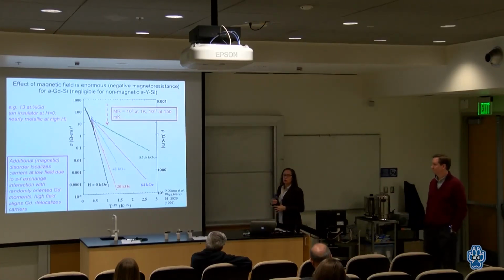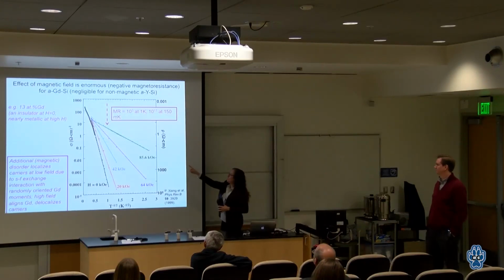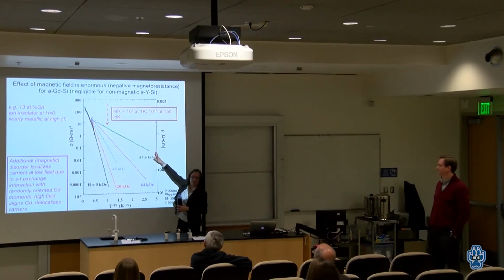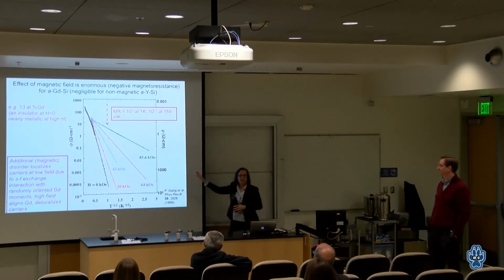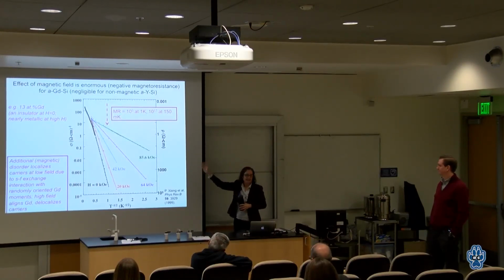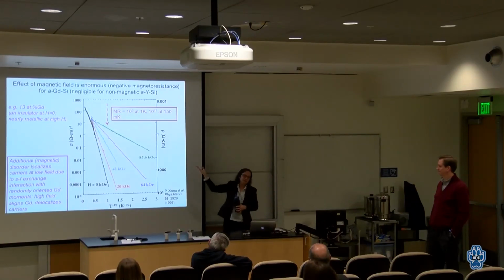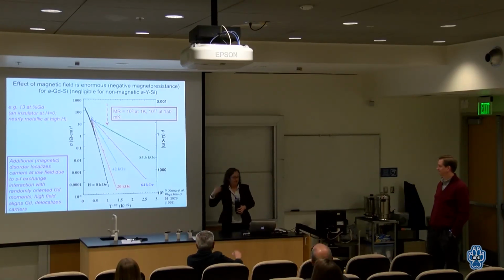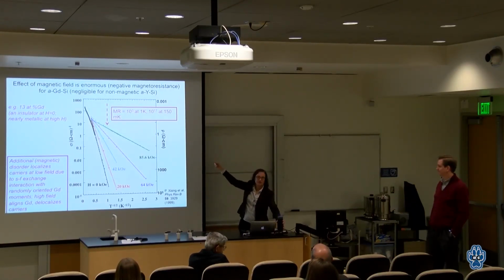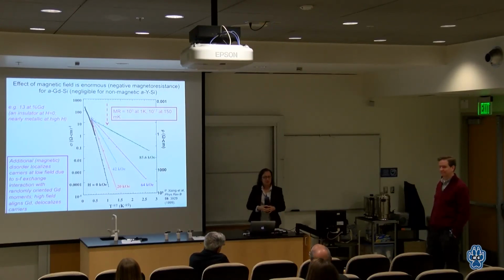No, we can keep going. 13% is just a really convenient one. It's the sample I measured that had the largest magnetoresistance. If I get more insulating, like 12% or 11%, I can't measure them. They get so insulating that I can't measure them. And if I go up to higher percentages, I actually go right through the metal insulator transition, but the magnetoresistance is not as dramatic. So I've gone through the metal insulator transition, but the number is not as big. So it's sort of a trade-off of what I plot. But there's nothing magic about 13.